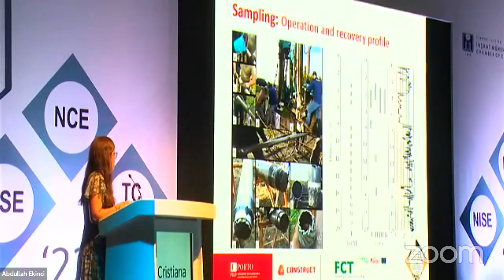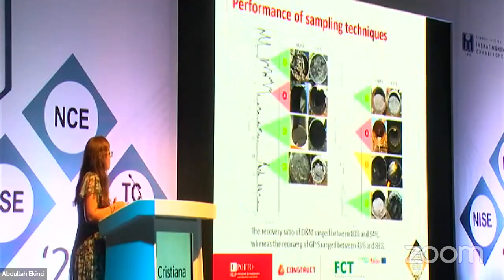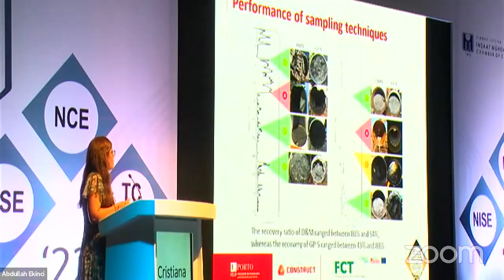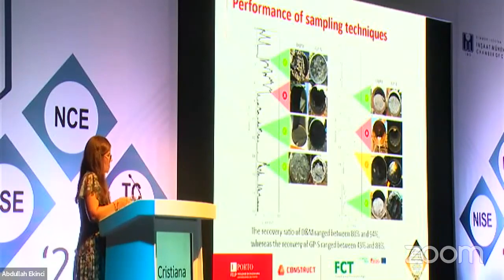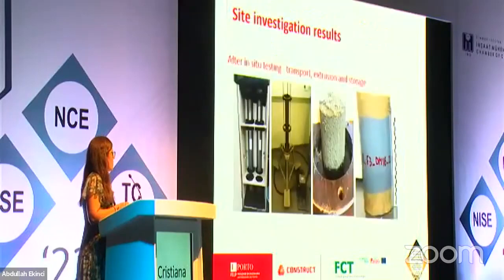In the gel push, we had some difficulties associated with precisely the gel condition, and in experience, it's because it's a brand new sampler, but in general, very successful in both samplers. And you see here where we have best results and a comparison at specific depth of the performance of the Dames and Moore and the gel push during the sampling process. So in the Dames and Moore, we have slightly higher recovery ratio, and there are a few that collected just a few shorter samples because of some particularities during the sampling.